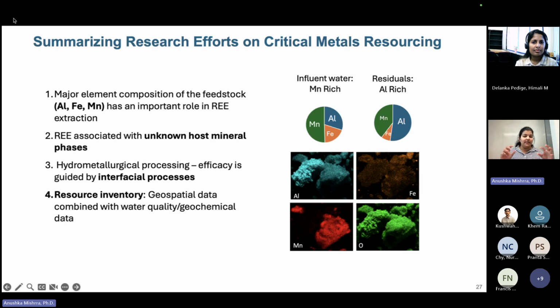composition, and we still may not know the actual form of oxides or silicates that are present. More work needs to be done, but we can start identifying there's an aluminum, there's a manganese dominant phase, there's an iron dominant phase, silica dominant phase. So we are getting there. Of course, the next step is to see where the REs are, where is the cobalt, where are the transition metals, where do they sit on these different phases.